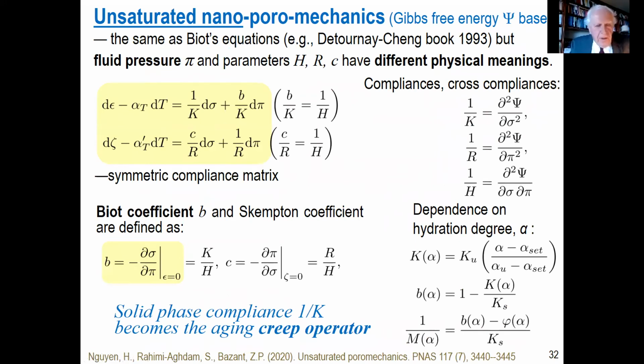So we get finally to poromechanics, and the difference is that this is an unsaturated poromechanics, which has not really been formulated before. Now, obviously, the poromechanical equations must have the same form as the classical Biot equations. So these are Biot's equations classically, and in his formulation, it was actually the pressure of liquid water in the pores, like of sand, fully filled. Now it's a combination, an effective pressure of vapor and adsorbed water and hindered adsorbed water, all these phases. This is only the volumetric part, so this is the volumetric stress in the solid phase. This is in the liquid phase, equivalent pressure.